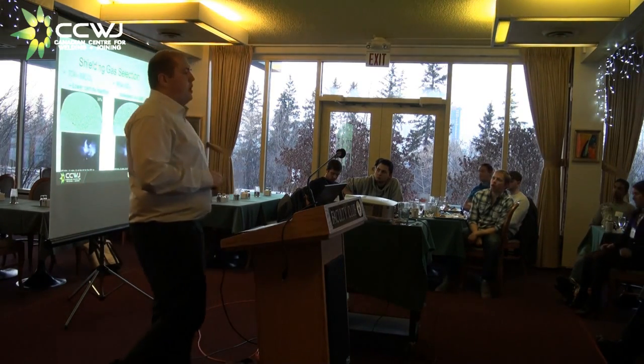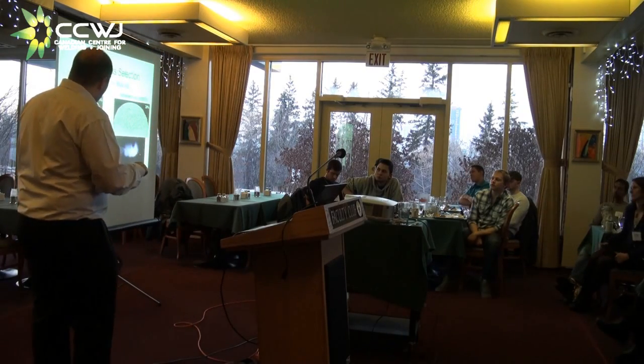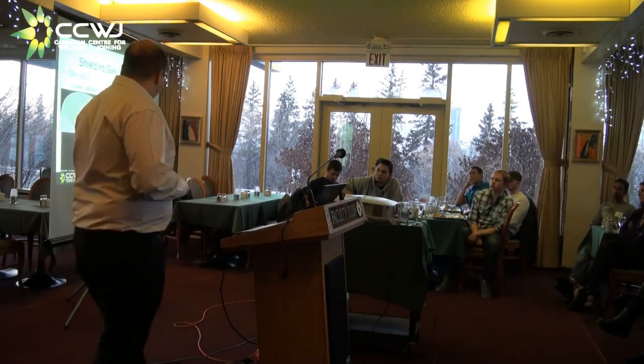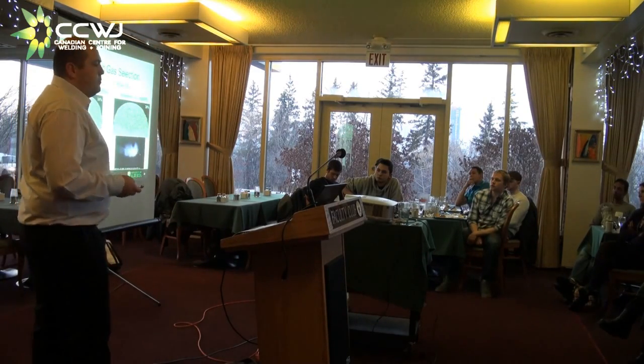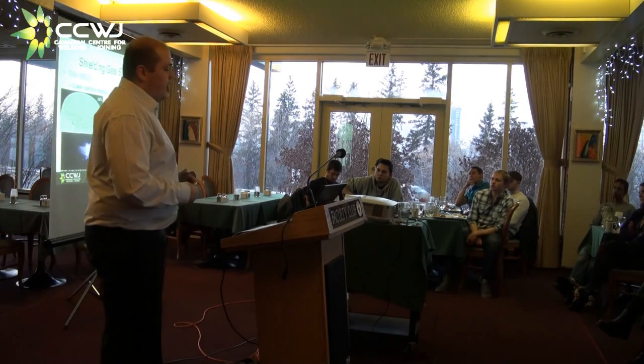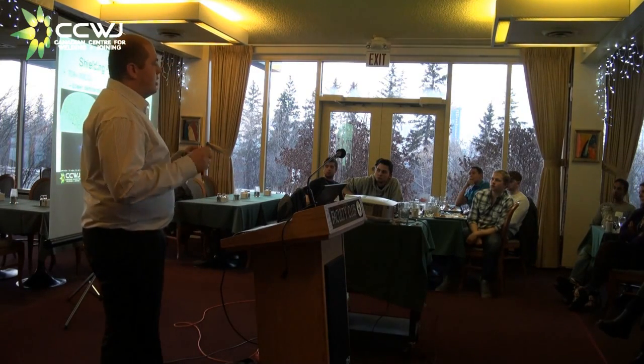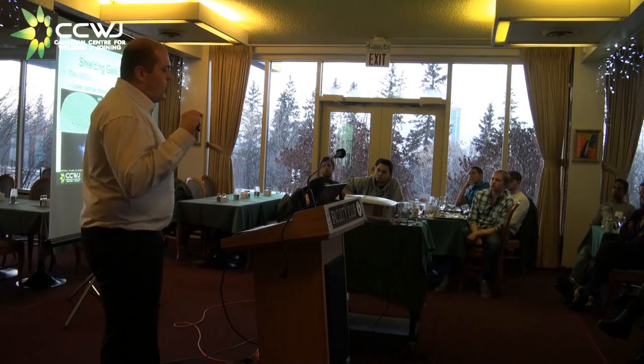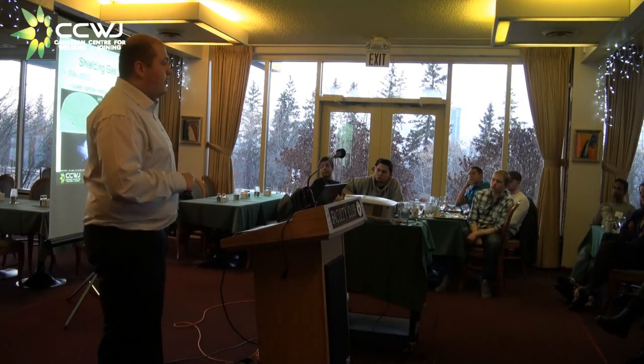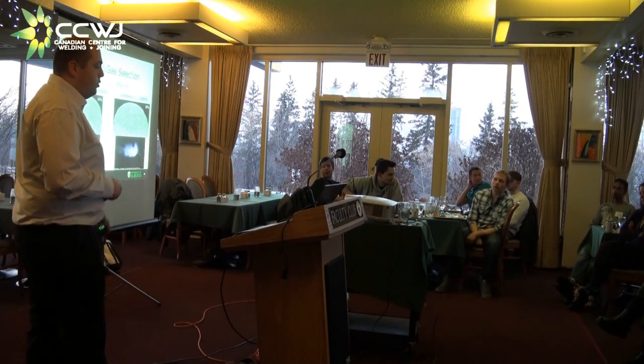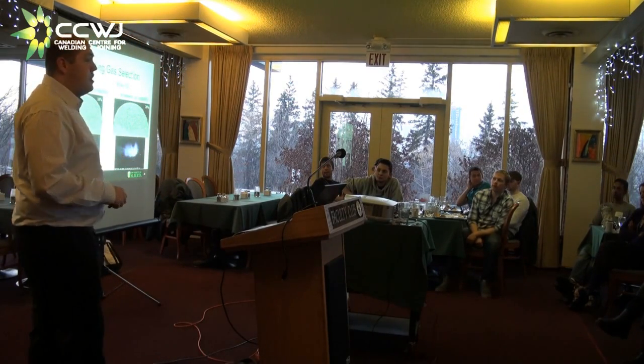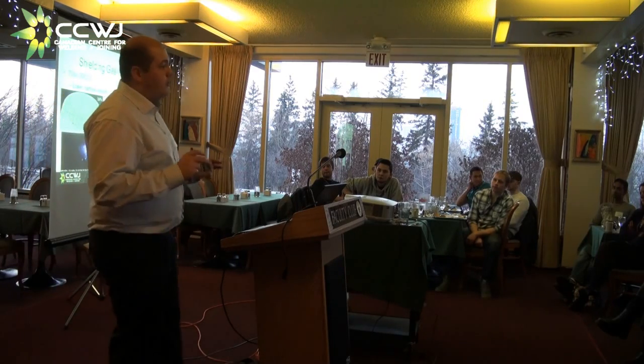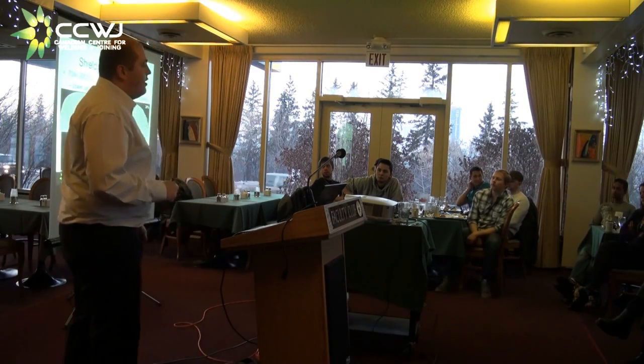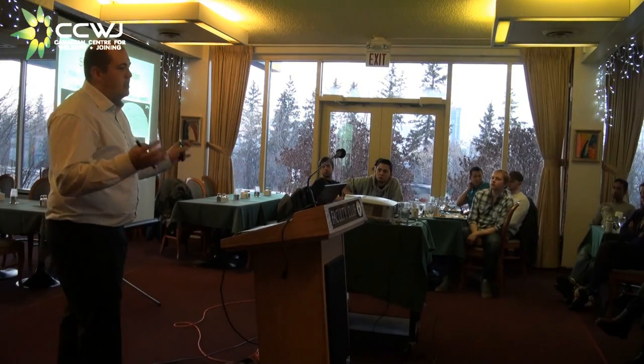Shielding gases also play a big deal. And just in case, these are all welds done in our lab with our high-speed cameras. Shielding gas plays a big deal in carbide fraction and arc stability. Now, here's the caveat. This only applies to just this one consumable that we tested. If I were to use a different consumable, the effect of argon or oxygen might be reversed, it might not. It is very hard to tell. So that's why you have to use wire A with shielding gas A. It makes a big difference.